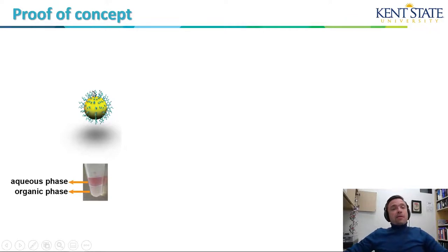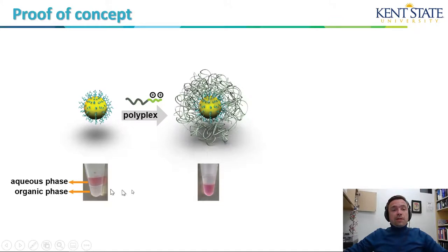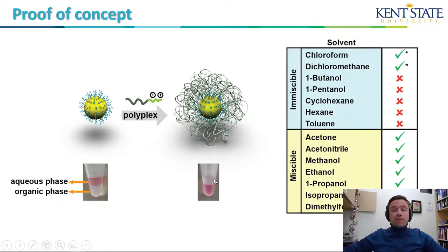And chemically, we hypothesized that these covered gold nanoparticles are very similar to DNA origami, which also has DNA on the outside. So we started by layering some organic solvent, chloroform, which is denser than water, below the aqueous phase. And then we added a solution of the block copolymers, shook this, and within seconds, the red color migrated into the organic phase, showing that this block copolymer micellization of the gold nanoparticles indeed initiated a phase transfer, which was even almost complete.